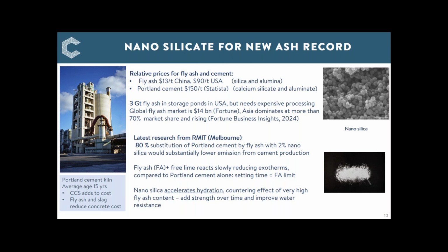The latest finding is perhaps the most interesting, and that is that you can create a concrete with 80% fly ash, replacing Portland cement if you add nanosilica. And I have a picture of the nanosilica on the right. It does need careful handling from a health and safety point of view, but the potential is significant in terms of reducing the cost of material and avoiding energy use.